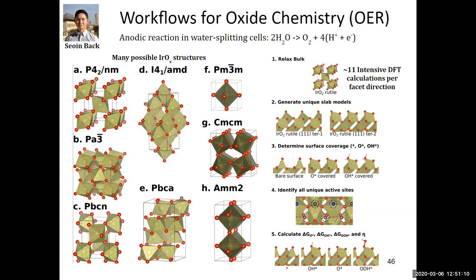It can be bare with a bunch of coordinated, exposed metals. It can be oxygen terminated. It can be OH terminated. Which one of those you get depends on where you are under reaction conditions and which one's the most stable. So you have to be able to consider this additional degree of complexity if you want to move to oxide materials. And that's on top of all the complications of how do you even model oxide electronic structure. So this gets really, really complicated.